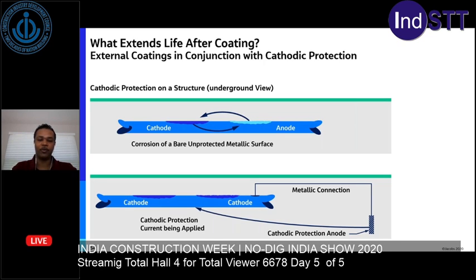And at the bottom photo, you see where cathodic protection has been applied. An anode was attached, which is a more active metal than the structure you're trying to protect, where the anode begins to corrode and the pipe becomes the cathode, to be cathodically protected, hence the term cathodic protection. Next slide.